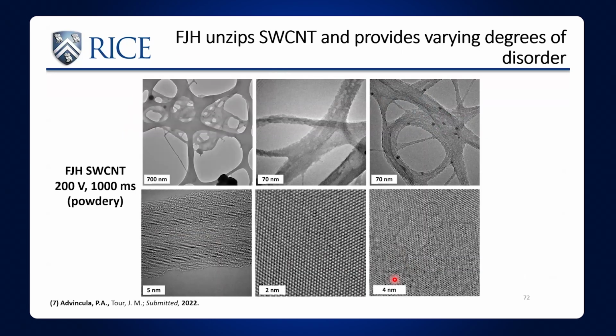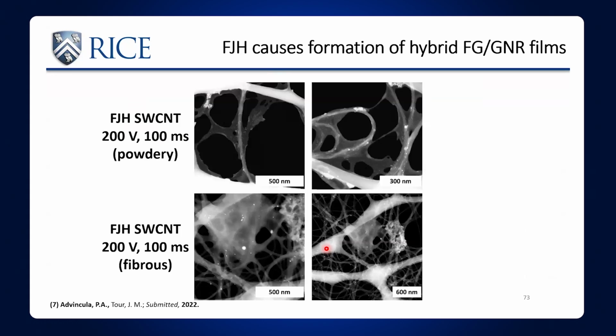And so you can see this by TEM. You can see areas where you have nanotubes. You can see areas where you have graphene. And so they're kind of mixed together. And so this is what you see here. Here you see some nanotubes, and then you see graphene going between them. This graphene and the nanotubes fusing in with the graphene.